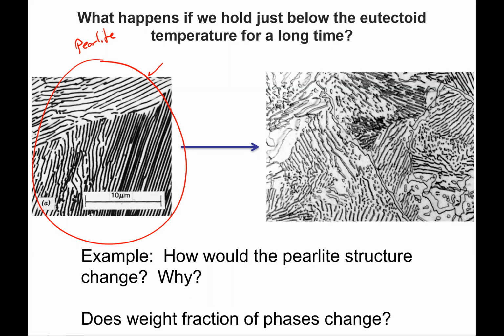But this particular material, as pearlite, really has a fairly high energy because it has a lot of phase boundaries. And all these phase boundaries are defects. So if we were to heat this up or maintain it at a high temperature and keep holding, then diffusion would start kicking in, and we would eventually start breaking up the layers, as you can see going on here. We'd start widening the layers, and the longer and longer this continues, we would eventually break up all these layers and form spheres of cementite. The reason we want to go to spheres is because spheres have the smallest surface area, so in this case meaning phase boundary area, relative to the volume. And so if we can break the structure up, coarsen it, eventually get it into spheres, then we're helping to reduce the energy of the phase boundary area in the structure.